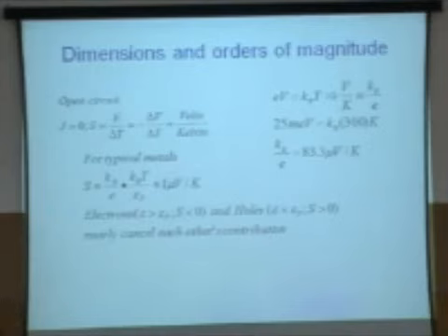Typically, metals, which are very good conductors, one would love to use because ZT is proportional to the conductivity. I can make it very large. Unfortunately, due to simple physics, they don't have large thermopower. That's the 83, but there is a Pauli suppression factor, kBT over EF. That gives you about 1 microvolt per Kelvin, and ZT is proportional to the square of that, so it's no good. So metals are not very good.